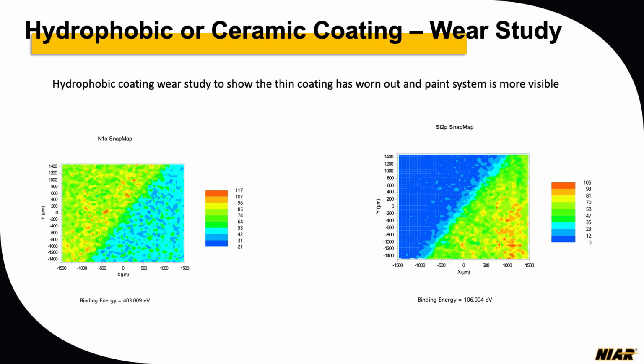So this is an example where we basically identified that this was a silicon-based coating, and this is your Taber wear resistance, your standard Taber wear where you basically run through a cycle and see how that coating lasts. So that gave us a very good detail of how many cycles comparatively it lasted. That is more revealing than an answer of, okay, if we have that coating, some of them say, even if it wears out, we still have the coating in there that will still protect or give hydrophobicity. But if you don't have a silicon or a fluorine component, which is one of the main ingredients, and it's just on the top layer, once the first cycle has gone through, it's sometimes completely worn out. Some of them might last longer. It depends on how your chemistry is built up. So this was one of the examples, and this is the data that shows that it has completely worn out and you're basically getting your coating system more.